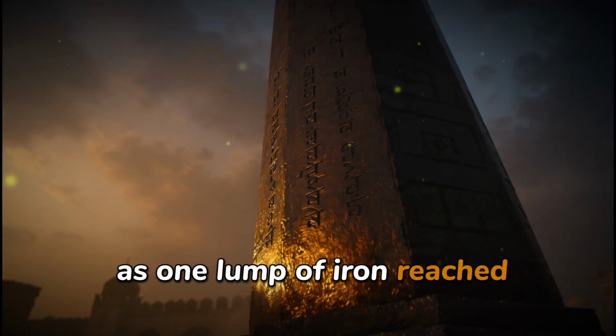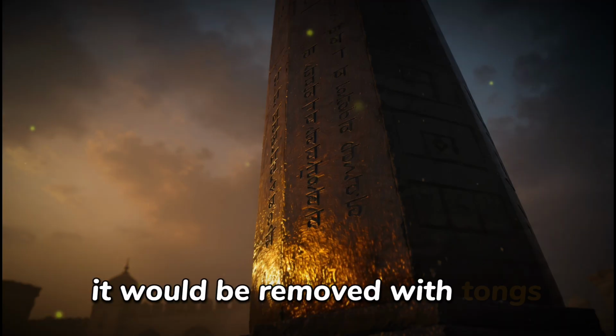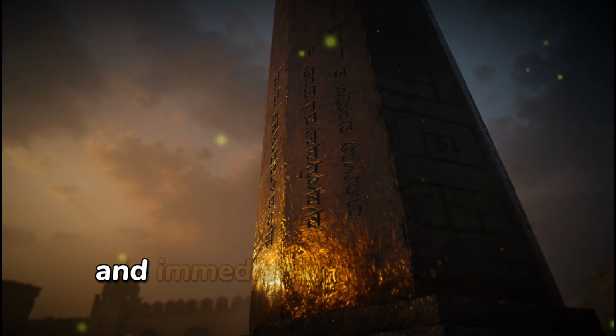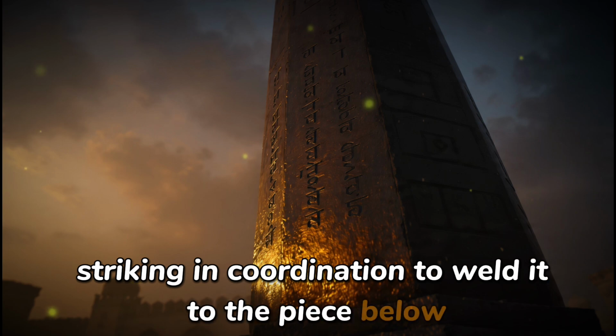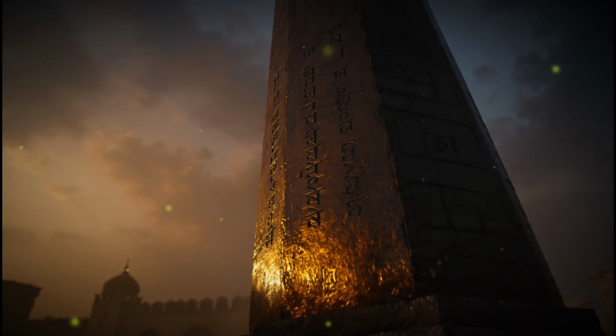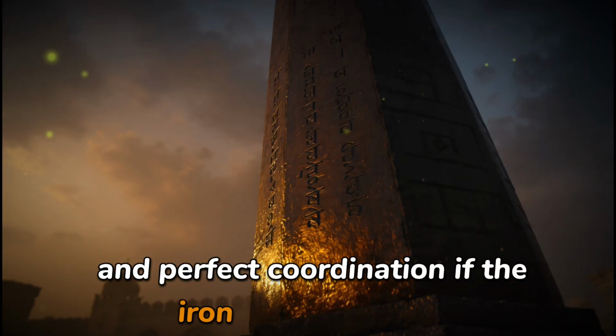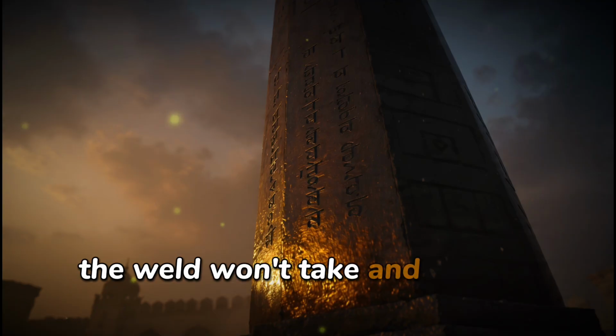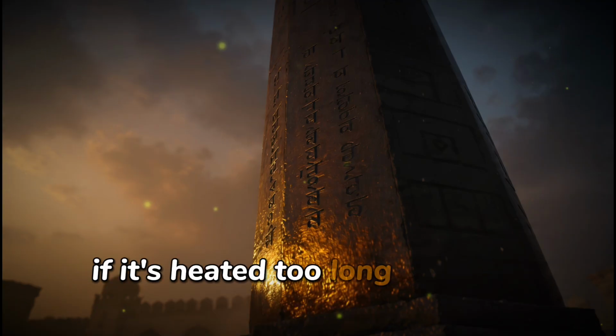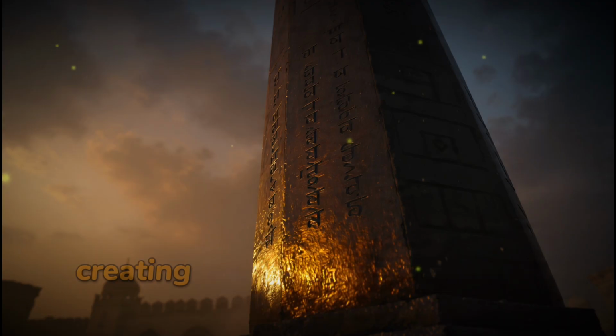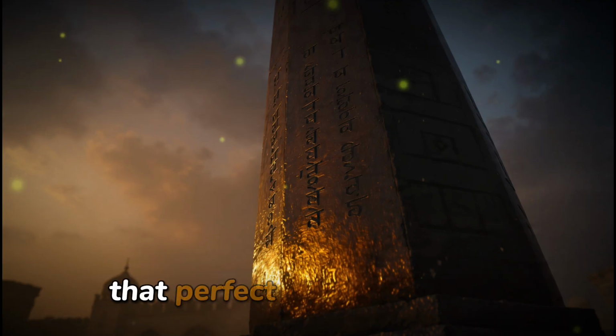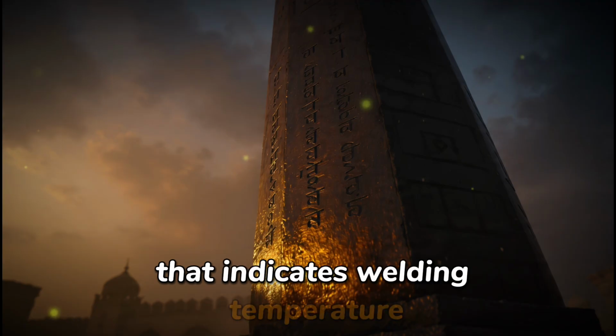As one lump of iron reached welding temperature, it would be removed with tongs, placed atop the growing pillar, and immediately hammered by multiple workers, striking in coordination to weld it to the piece below before it cooled too much. This process requires split-second timing and perfect coordination. If the iron cools too much, the weld won't take, and the joint will be weak. If it's heated too long, the metal oxidizes excessively, creating slag that prevents proper joining. The smiths had to know, by experience, the exact moment when the iron was ready, that perfect cherry red colour that indicates welding temperature.